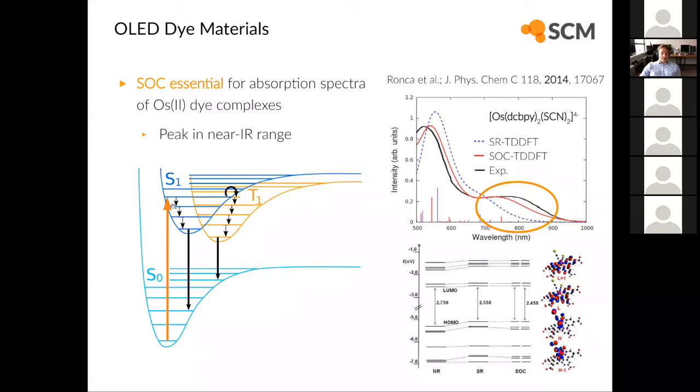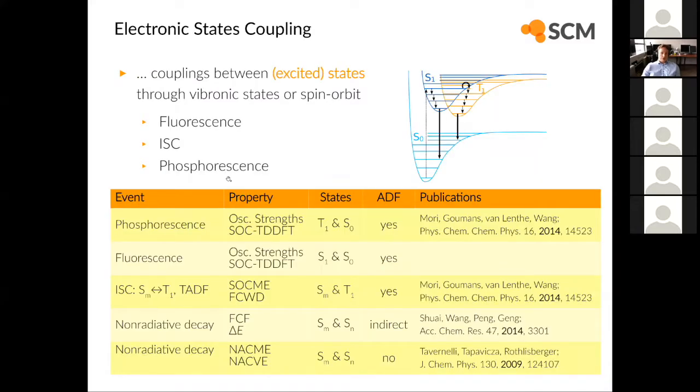So basically, one excites the system from its electronic ground state into an excited state. However, when it comes to OLED materials, one usually has to deal with different kinds of phenomena. For example, usually one has charges which meet in the OLED layer, and then these charges, so basically electrons and electron holes, when they meet, form excited states. They can be either singlet or triplet states, and then there are all kinds of different pathways possible between which the system can then transfer or